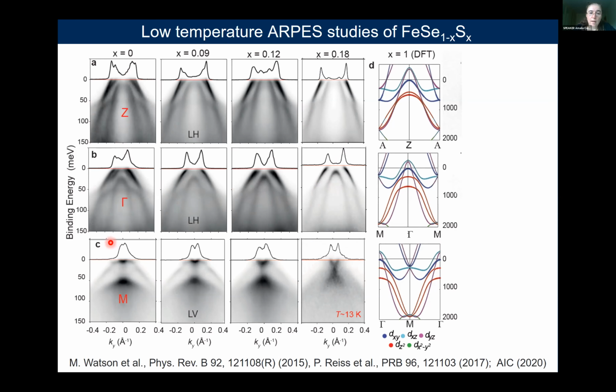But more striking is the effect at the end point. As I discussed, here we are expecting two dispersions. The outer one is supposed to be dxy character, but because of its very strong renormalization effects and becoming more incoherent, it is much harder to observe in experiment. Just a little shoulder is seen in these momentum-dependent cuts. This shoulder is barely visible, but more striking is the band under it. As we turn on the nematicity, going from the right to left, these two points split, and this band shifting effect becomes very significant, reaching a value of about 50 milli-electron volts.